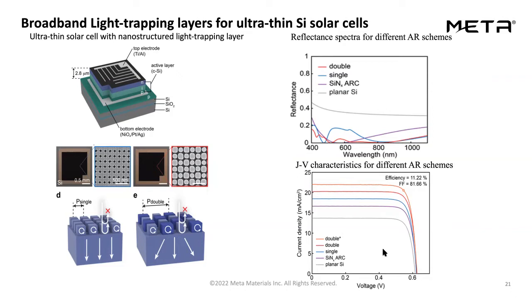As we apply these different coatings, including the optimized silicon nitride ARC coating, which is the standard coating that people use for these solar cells, our coatings, which are these metamaterial elements, can increase the efficiency up to 22 milliamps per centimeter square. And this is an 11% efficiency increase compared to the standard ARC coatings.